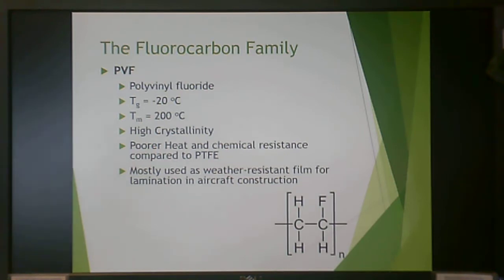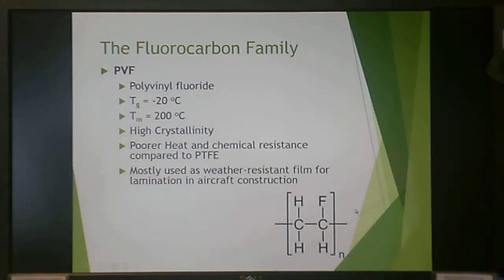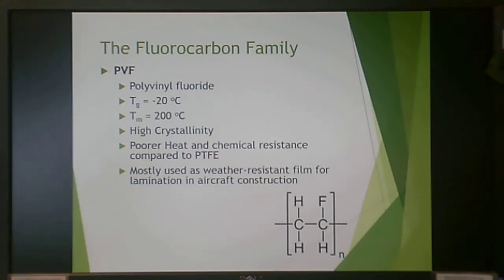Polyvinyl fluoride is the fluorine version of polyvinyl chloride — where PVC has a chlorine atom, PVF has a fluorine. It has a TG of -20°C and a TM of 200°C. It is highly crystalline with poorer heat and chemical resistance compared to Teflon, and is mainly used as a weather-resistant film in lamination for aircraft construction.